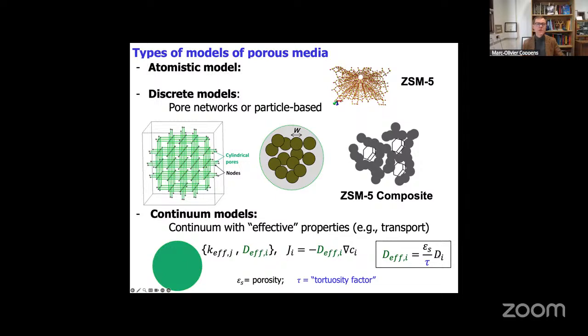But because the pores are not all straight, not everything is smooth, we also need to have a factor, tau, that is a tortuosity factor, put between quotes. And this is what much of this talk will be about, of how we evaluate this. In fact, Rutherford Aris, very famous founder in our discipline in reaction engineering, called this a fudge factor already several decades ago, because it is purely a factor where we try to fit results, especially when we compare experimental results with theory, after we put in some value of tau in our reactor models